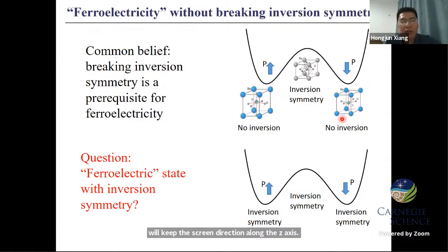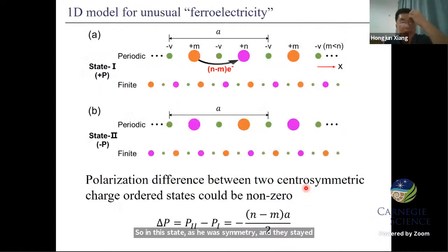Maybe I will use one or two minutes to introduce our recent work. Usually people believe that inversion symmetry breaking is a prerequisite for ferroelectricity. For example, in barium titanate, the paraelectric case has inversion symmetry, but the ferroelectric structure has no inversion symmetry. So we are trying to answer whether it is possible to have a ferroelectric-like state with inversion symmetry. This state has inversion symmetry, and this state also has inversion symmetry. So we consider a one-dimensional model for this unusual ferroelectricity.